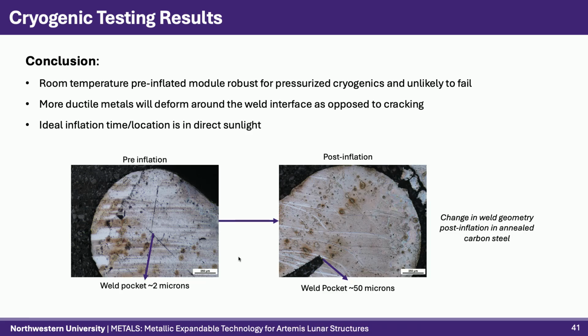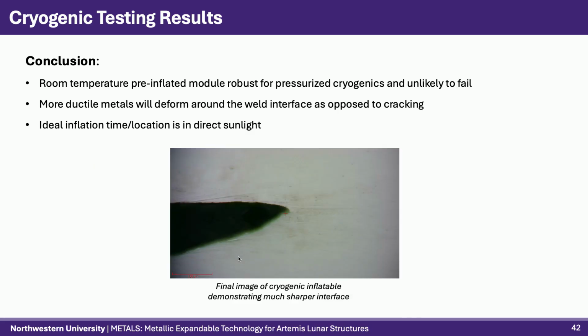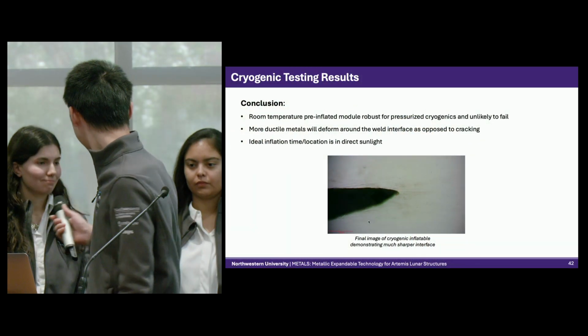The reason why we think colder inflatables are more likely to fail is because colder metals are less able to deform to relieve the stress that is placed on them. If you look at this weld picture, you can see that the weld pocket increases in size for the room temperature inflatable from about 2 microns to about 50 microns. But importantly, the end is blunted, which means the crack is less likely to spread and cause failure. For this cryogenic sample, you can see that while the weld pocket increases less in size, the end is unblunted, which is likely to fail.